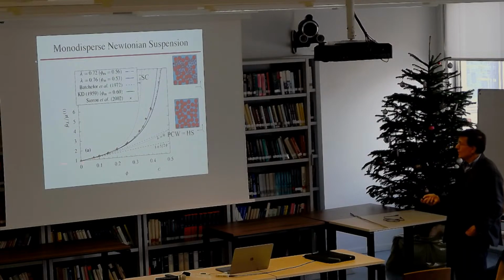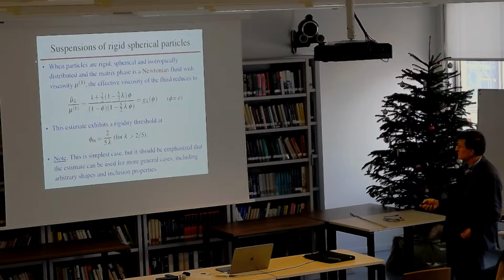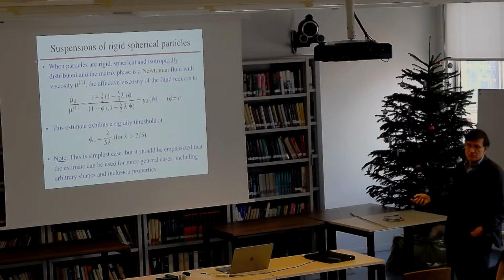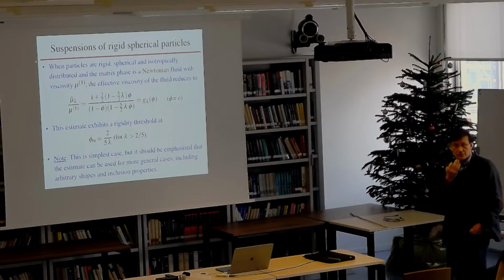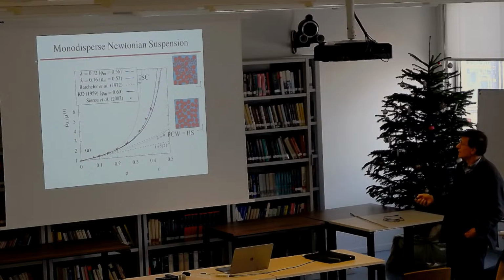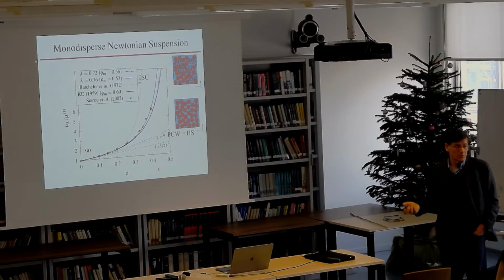In any case, we have that result. And if we say, we have this formula here, valid for any volume fraction, suppose we take an expansion of this to second order in the volume fraction, and we match the term to the exact result of Batchelor's. Well, that's what gave us lambda equals 0.72. So you get something that agrees to second order in the volume fraction with exact analytical results for monodispersed systems, and it gives results that are quite reasonable for large volume fractions.